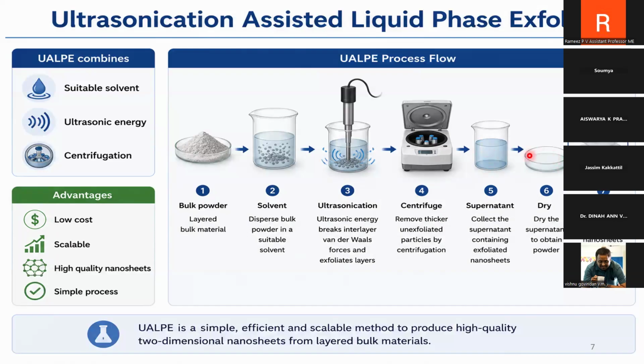And in that supernatant, we have the exfoliated 2D material, whatever. It could be graphene, it could be hBN, whatever. As we have that 2D material inside the supernatant, we need to dry it. That's the only way you can actually take out this HBN, sorry, the two-dimensional nanoparticles. So by drying it, you get nanosheets. Now I call it nanosheets, not nanoparticles.